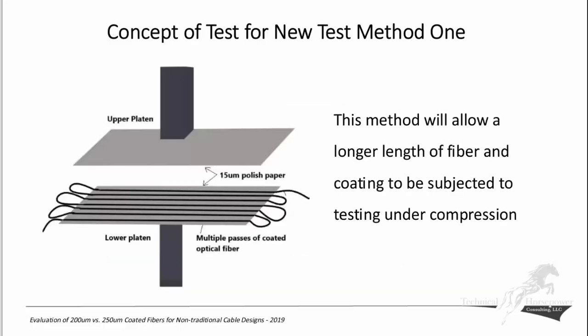So in that vein, we came up with this concept of taking an existing test, EIA/TIA FOTP-41A, a crush test, and it uses valuable design data because it crushes things. But what happens if you now have aramid yarn coated with superabsorbent polymer in a dry crystal form in contact with the fibers? The problem was that we only had 10 centimeters of distance under that test. And with our super deluxe, and I'll use that nice term for it because I think the fiber guys have done a fantastic job of developing super low-loss single-mode optical fiber, over 10 centimeters you really can't see an increase in attenuation that would be substantial over an entire length of cable. So we needed a longer gauge length.